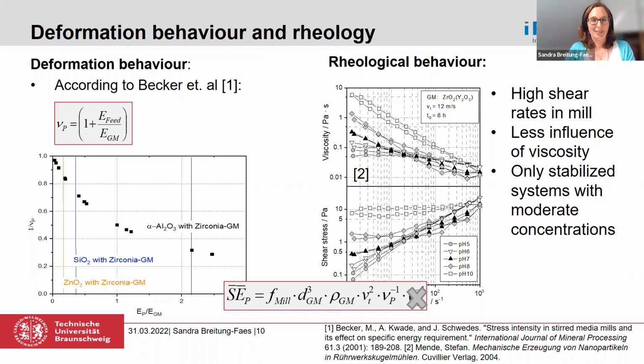And you would say, okay, I think grinding beads won't move that much. But as we know from the Newton-Reynolds relations in mills, there are very high shear rates. For our rheometer, the maximum value was 1,000. And from the back calculation of the Newton-Reynolds diagrams, I came up with values which were roughly one or two decades higher than this 1,000. So I decided to neglect the rheology value, because I think in the mill itself it won't play a role. It will play a role within your periphery for sure.